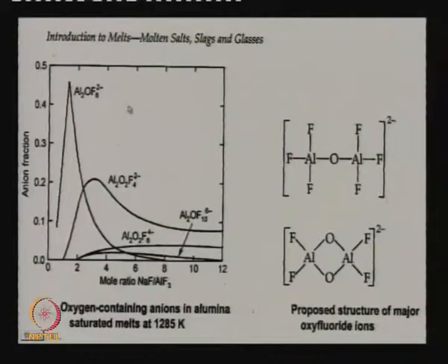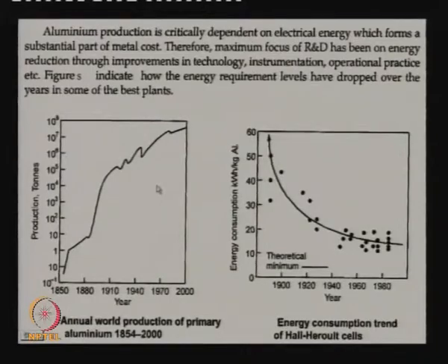There are all kinds of anions existing there, and because of their existence there is evolution of fluorine gas, there is evolution of other gases that you do not want. Not only do they cause contaminants in the environment, they also bring down the current efficiency through undesirable reactions.